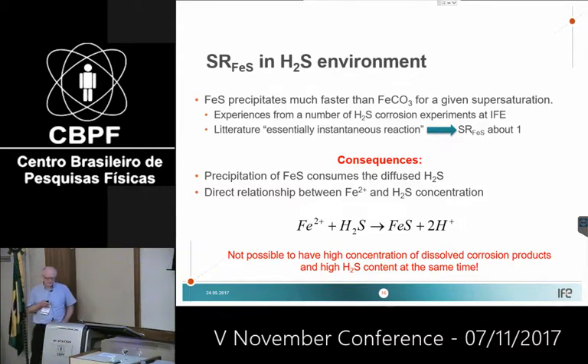And that is based on experience from a number of experiments, and there are publications stating that it's essentially instantaneous precipitation, and that indicates a supersaturation of 1. And that has large consequences, because the precipitation of iron sulfide will consume the H2S that comes into the system. And it's a direct relationship between iron and the amount of H2S in the environment. So it's impossible to have a high concentration of dissolved corrosion product and a high H2S content at the same time. Either you have a high amount of corrosion product and low H2S, or you can have it vice versa.